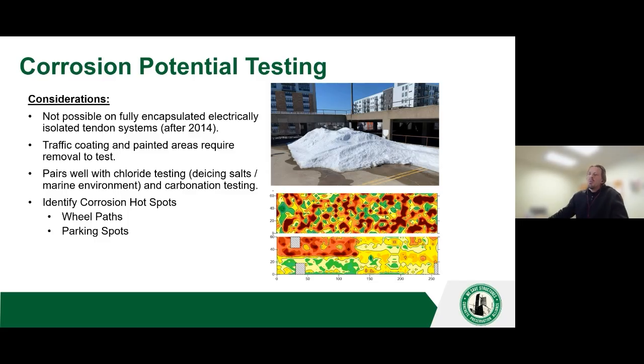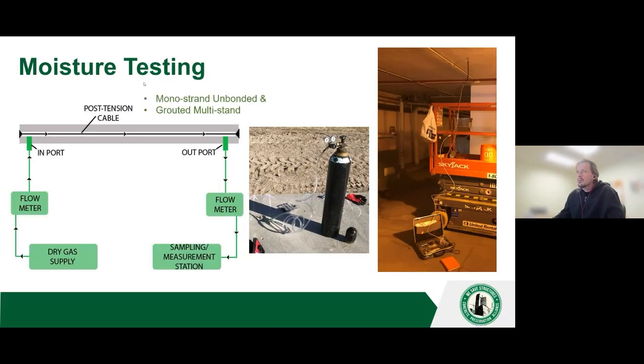And then we want to identify corrosion hotspots, right? Where are they in relation to our anchor lines, construction joints, wheel paths, parking spots. There are times when, if there's low spots or ponding on the deck of the slab, we're going to typically see higher corrosion potentials in those areas.